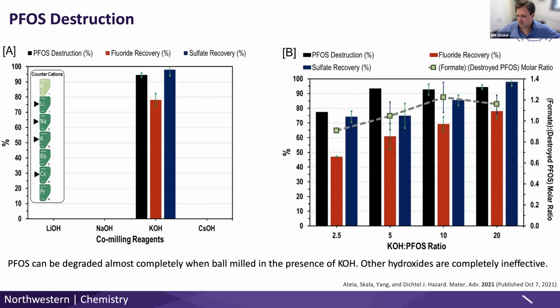And so we quantified the sulfate. What's the fate of the sulfur head group off of PFOS? We found that we got pretty much all the sulfate back that we expected. We got most of the fluoride. And now we're looking at this plot over here. We're getting 60 to 80% of the fluoride out, but not quite all of it. Then we're also looking at some of the carbons and what happens to those. At first we found formate, which was interesting, but only one molecule of formate for PFOS. So that accounts for one of the 8 carbons, but not the other 7.